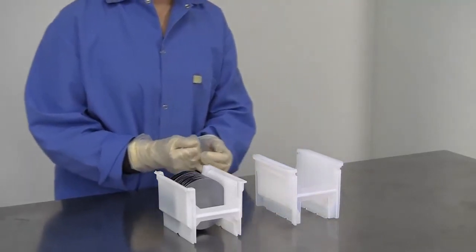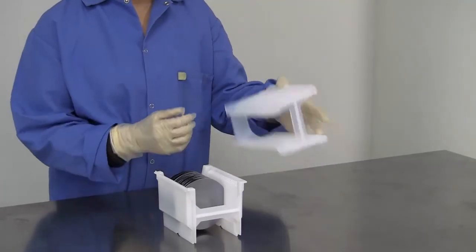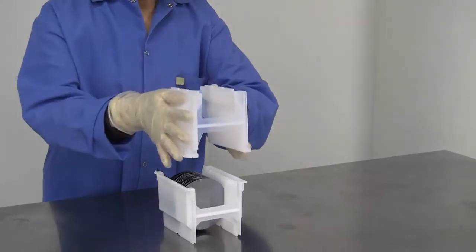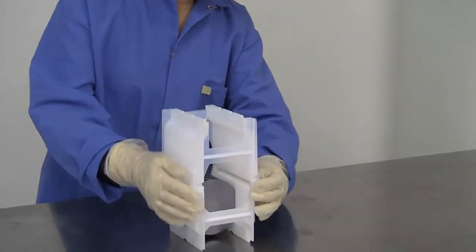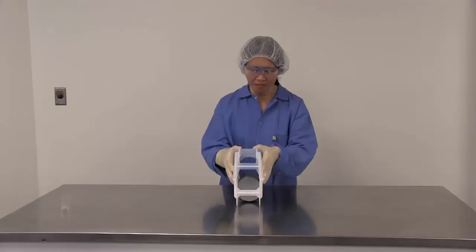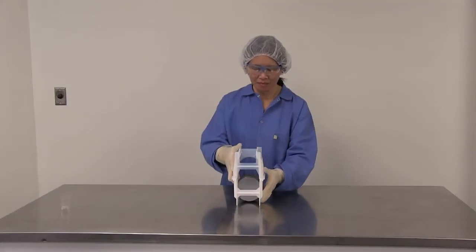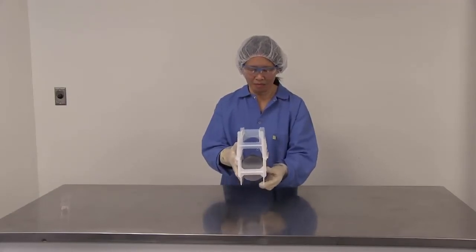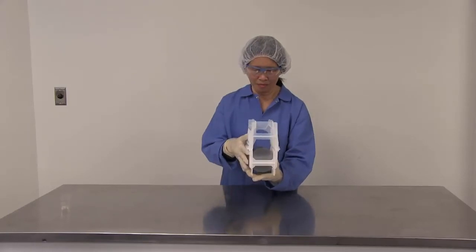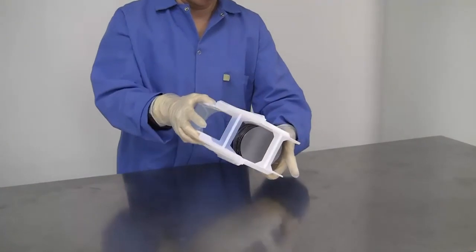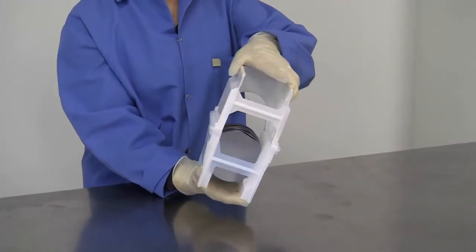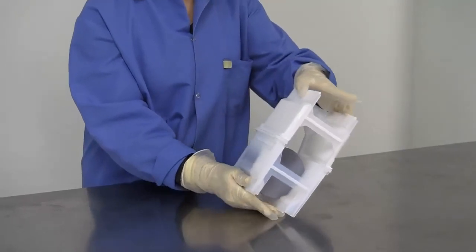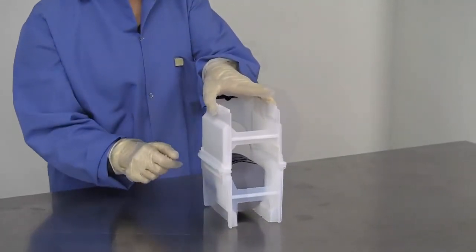Wearing clean vinyl gloves, place the receiver cassette upside down over the donor cassette. Make sure to fit the protruding pins into the alignment holes on both sides of the cassette. Firmly hold and lift both cassettes in both hands. Try not to flip the wafers, as the impact creates particles and can damage wafers under stress. Instead, gently tilt both cassettes so that your wafers roll from one cassette to the other. Your wafers have now been transferred.